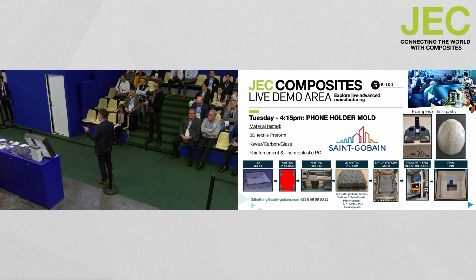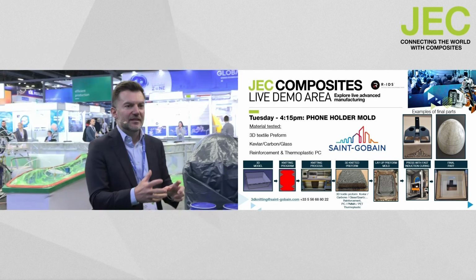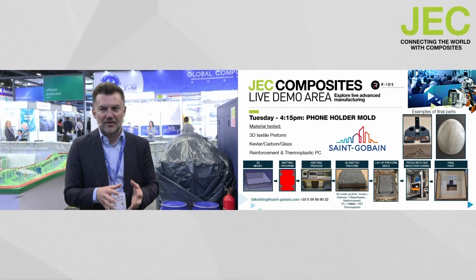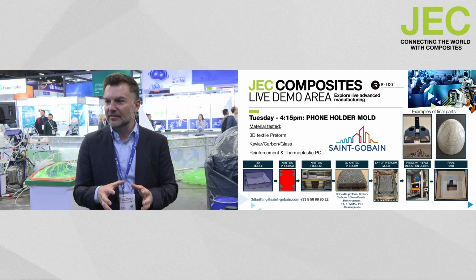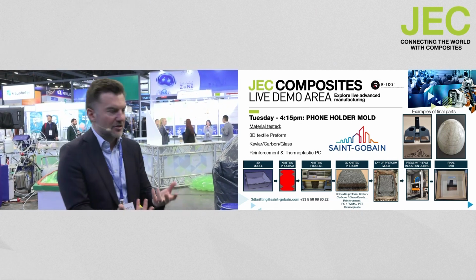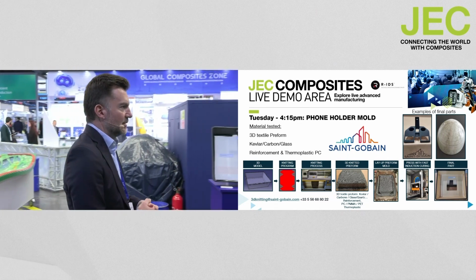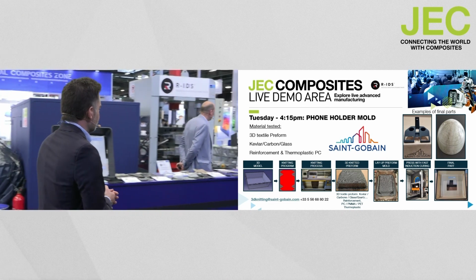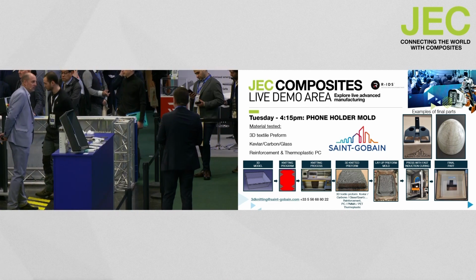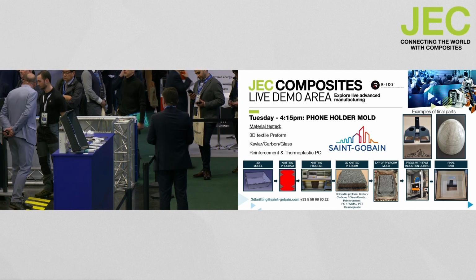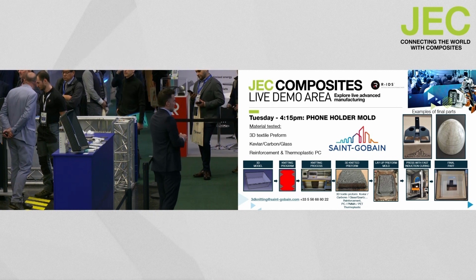So the platen temperature, I think, will remain fairly hot, a little less than 200. And right now, we're bringing the insert to demolding temperature, which I think is about 80, 70 C. And then we can handle the part, and you can see how the part behaves. Just again, a few seconds. We are at 130 degrees.